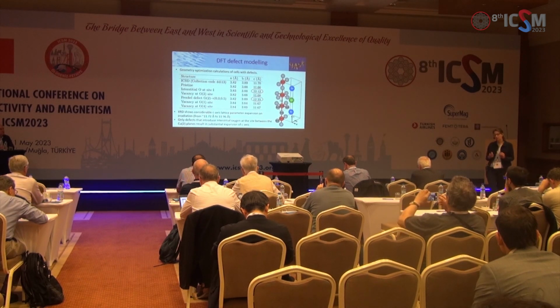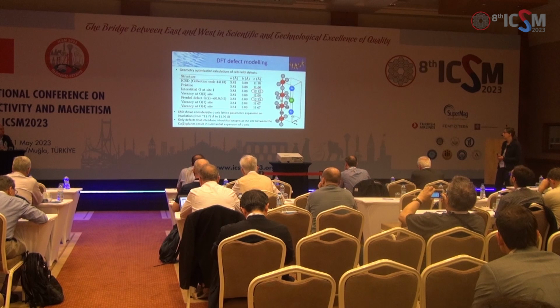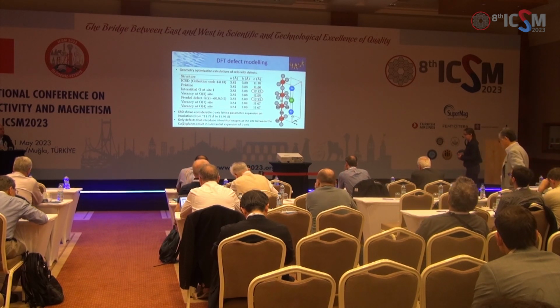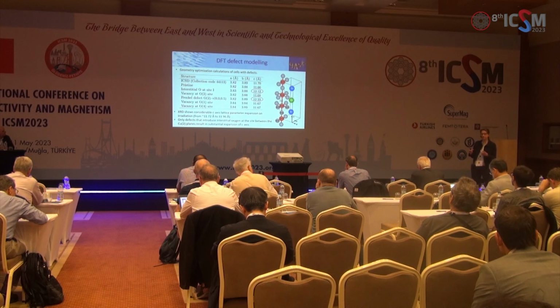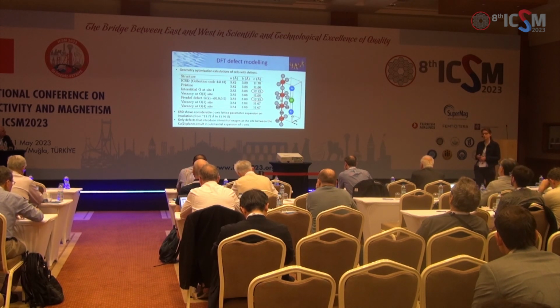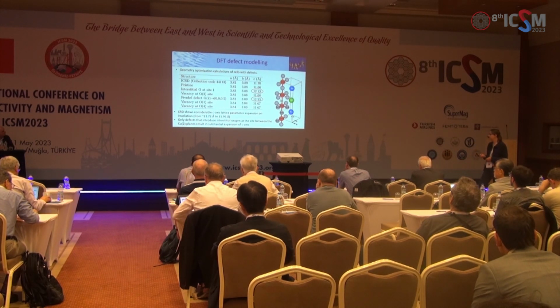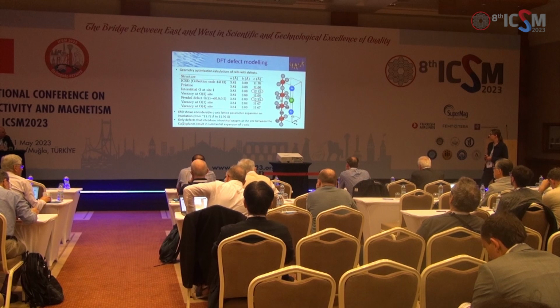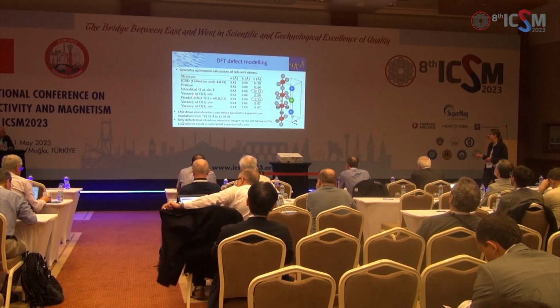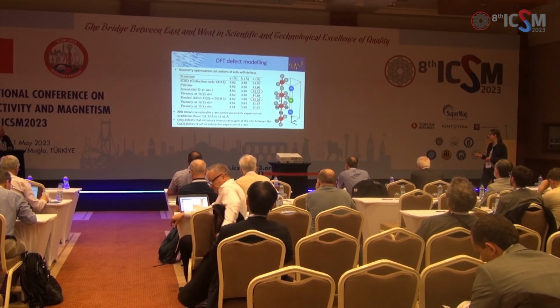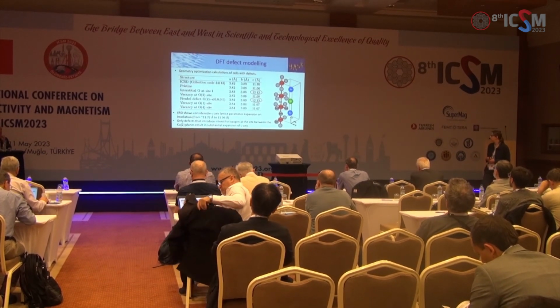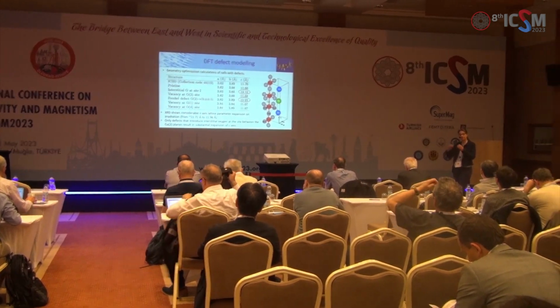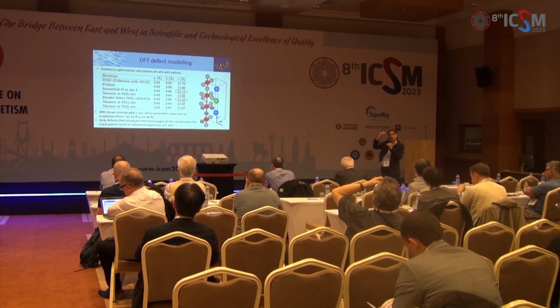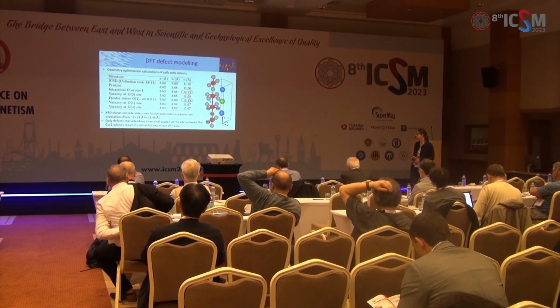If we want to find out a little bit more about the defects that we've put in, we can do some rather clever things with the DFT modelling. We can create supercells and make defects in those supercells, and then we can simulate what the spectrum would look like for particular defects that we put in. So we've done various different kinds of defect, and we homed in on a couple to look at, in particular this Frenkel defect here and the interstitial, because when we do X-ray diffraction, we see that the C-axis gets expanded experimentally when we do these irradiations.